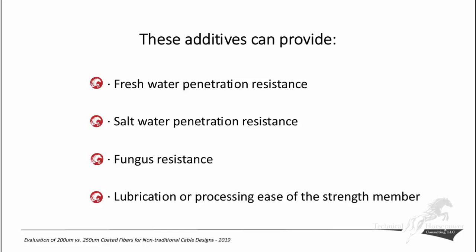So when we do all of that, if you just think about strength member types and the additives that go into them, it's a long list of unknowns. I'll give you a good example of a strange one, if you will. Think about a blown fiber tube that contains multiple fibers. And during the blowing installation process, you're shaking the tube and creating some aeolian vibration in there. Well, if you have a dry core and you have crystalline superabsorbent polymer in there with these fibers with a 200-micron coating, are you abrading the coating enough to damage the fibers?